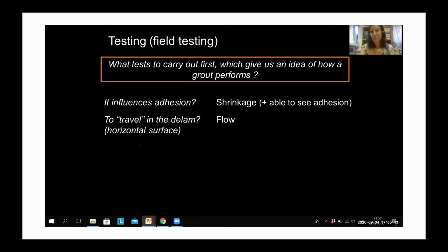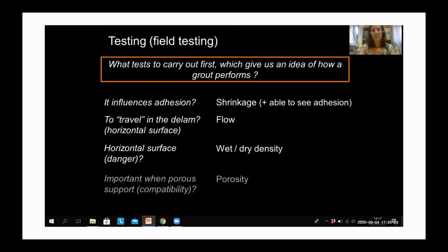Flow is important because we need to inject it. Very often wet and dry density is important, particularly if it's a horizontal surface, so if you're working on a vault or on a ceiling. And also porosity is very important because we want it to be porous enough to be compatible from that point of view with the original materials. Porosity, however, is often a quite complicated test to perform. So on the field, we usually do capillary water absorption tests.